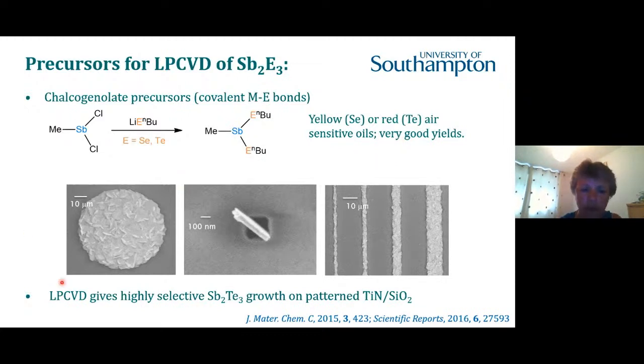And at the bottom of here, I've just shown you that the same principles that we saw for the bismuth telluride work beautifully in this antimony telluride system. So we can see that we can fill circular recesses, we can control the orientation of the crystallites, and we can also fill trenches to create what would ultimately be, for example, the legs, the individual elements of a thermoelectric device. So we can create arrays of these lines which are fully filled with antimony telluride to give the P-type material.